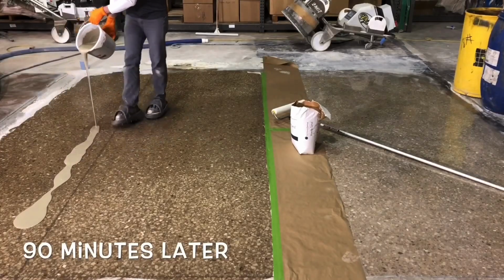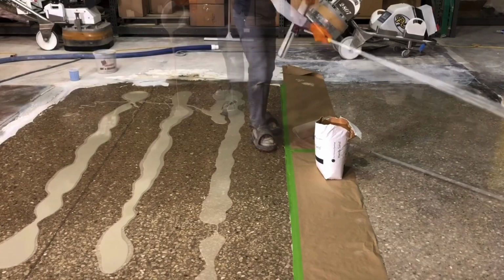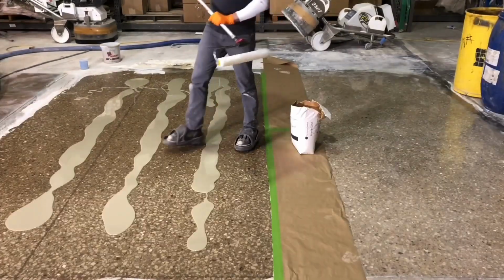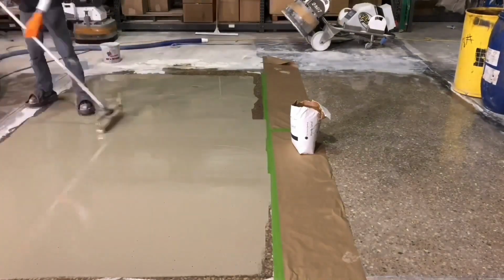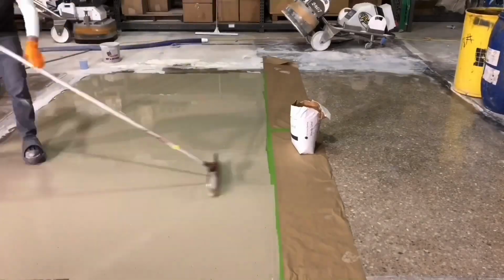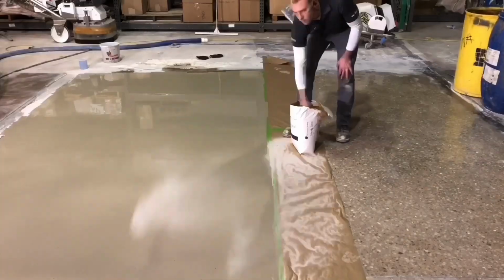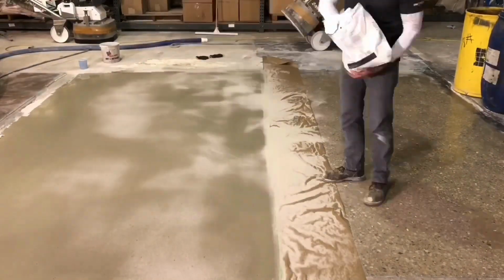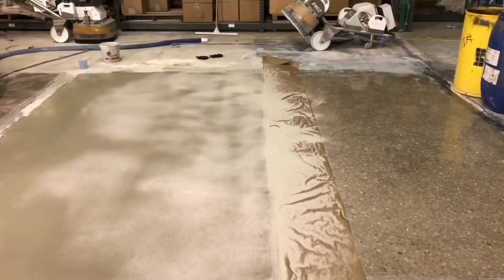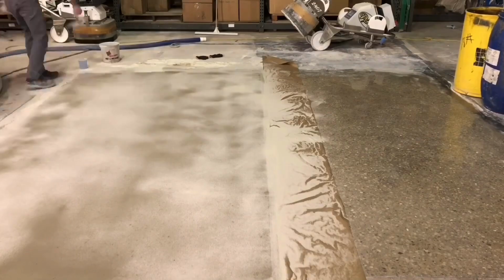Once the skimming was complete, it was allowed to sit for about 90 minutes. We don't really have to worry about the skim coat being fully dry as long as we have spikes when we go on the floor. We can put wet epoxy over wet epoxy primer or wet epoxy skim. The body coat was installed at 20 mils. Once that was complete, while it was wet, sand was broadcast into it until rejection. By adding sand, the compressive strength and the abrasion resistance of the epoxy will be increased.